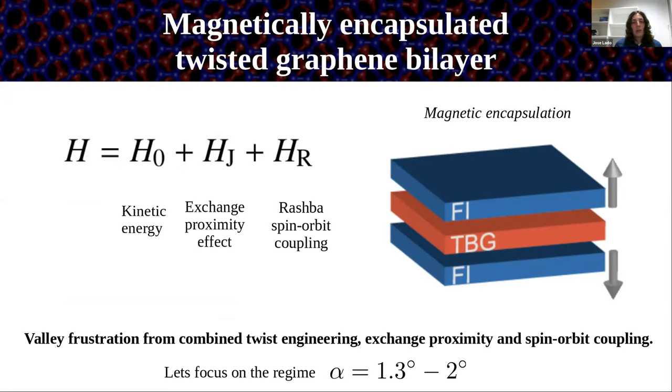So again, our Hamiltonian is going to consist of, let's say, three different terms. The first one is the kinetic energy, that is the conventional tight-binding model with several thousands of atoms per unit cell. That's the one responsible for flat bands and all the phenomenology that we know in twisted graphene bilayers. We're going to have also an exchange proximity effect that comes from a second order process to the ferromagnet. And we are also going to have Rashba spin orbit coupling in the two layers that comes from the local mirror symmetry breaking induced by the ferromagnet. And the regime in which we are going to focus is a little bit above the magic angle, so something between